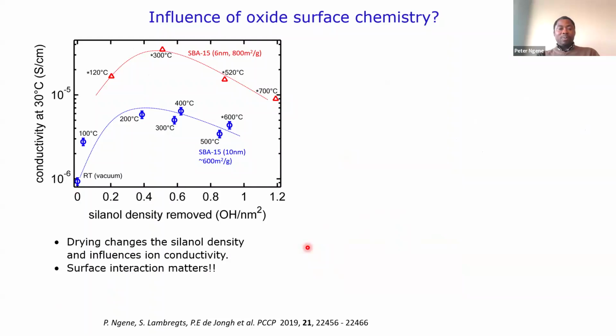With this, I think about the last slide. We say, okay, if the surface interaction matters, we know that we can tune this surface interaction. So we can really modify our surface. So here we just use this lithium borohydride. We confine it in different SBA-15. This is 6 nanometer, and then this one is about 10 nanometer.